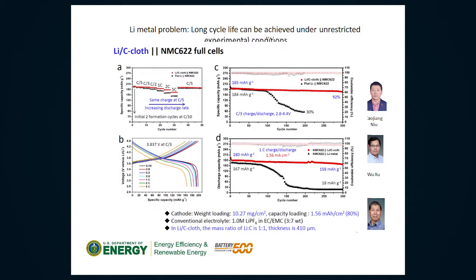If you go to the literature, there have been a lot of papers in the last few years about the stability of lithium metal. So these are the data we have. This is unrestricted. If we just have lithium metal and a very standard electrolyte, with nothing to protect the lithium metal, no additive, they fail pretty quickly. But this is again under unrestricted conditions: a lot of electrolyte and a very thin cathode. In this case, people report you can cycle lithium metal, if you do it carefully, with high Coulombic efficiency over a couple hundred cycles. That's really true, as shown by the data we're getting.